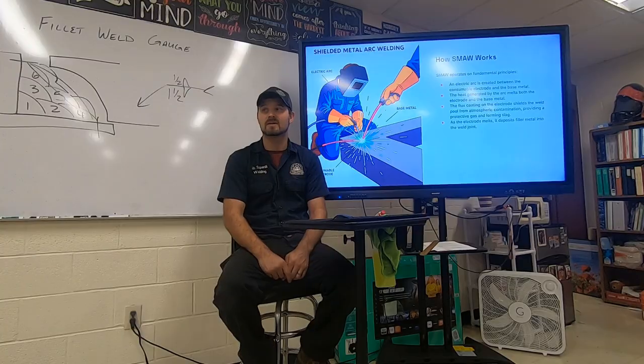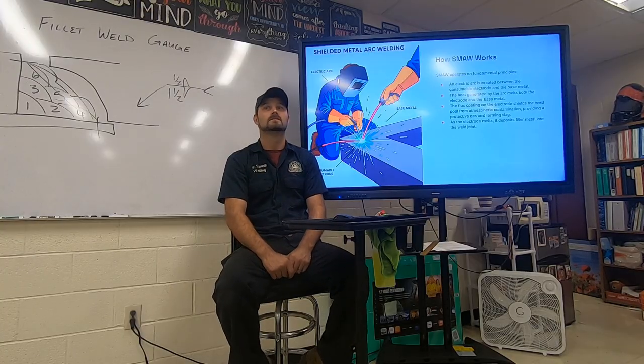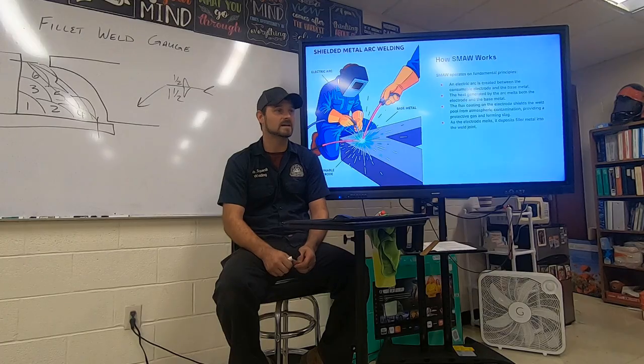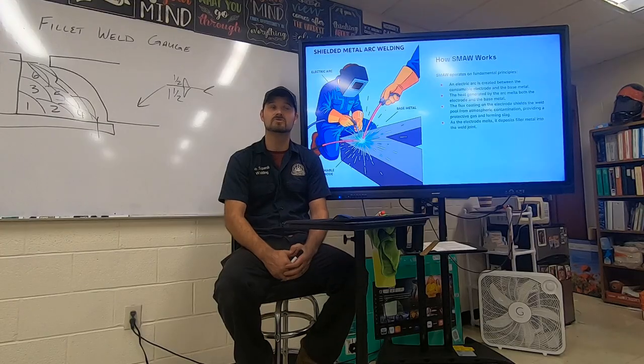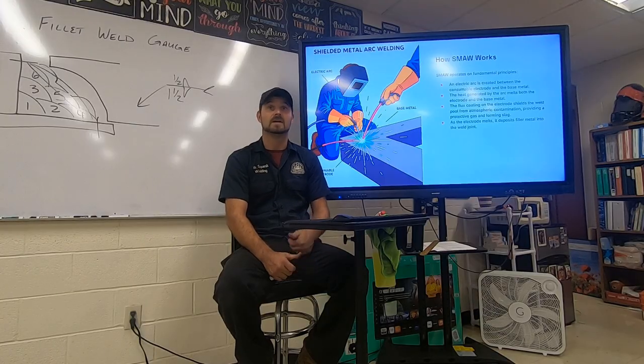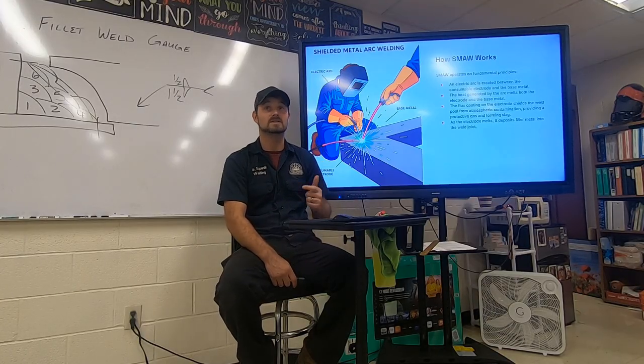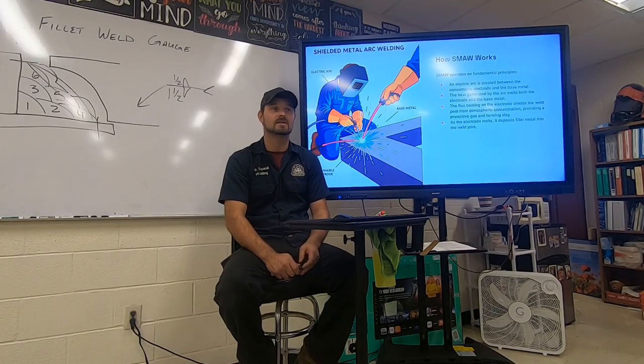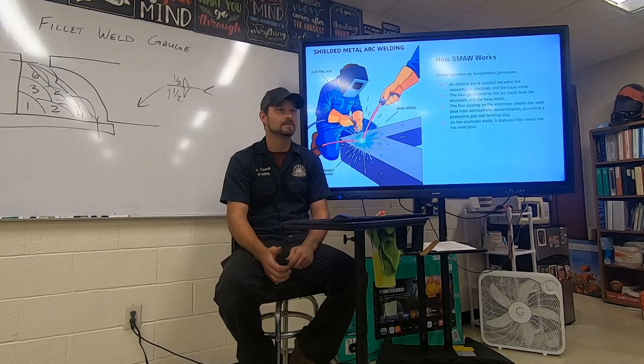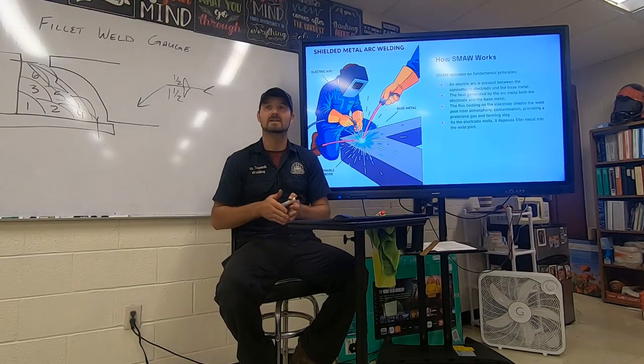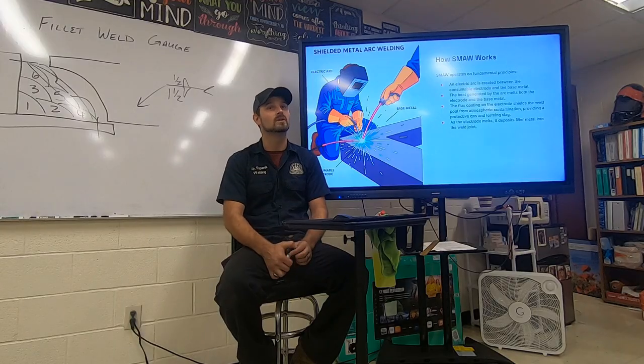Now, just like we talked yesterday about tensile strength, right? Let's say, for example, you're using a 7018 electrode. 7018 is a structural rod meant to hold things. The minimum tensile strength for a 7018 electrode is 70,000 pounds per square inch, okay? If we have a really good weld, but it's full of porosity or slag, we are not getting that 70,000 pounds per square inch strength out of there, okay? So we've not met the requirements for that specific rod, okay? Usually, if it's executed correctly, it's like 10 or 15,000 more PSI as far as strength goes with that particular rod.